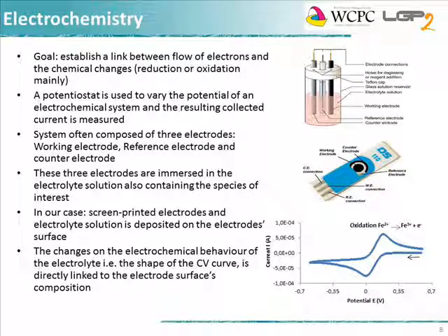In the case of our printing sensor, it's a bit different. You can see here an example of the industrial screen printed electrode on the right. In this commercial product, the 3 electrodes device is printed on substrate which is ceramic. The reference electrode is made of silver, the working electrode of carbon, and the counter electrode is made of platinum. The electrical contacts are made of silver.